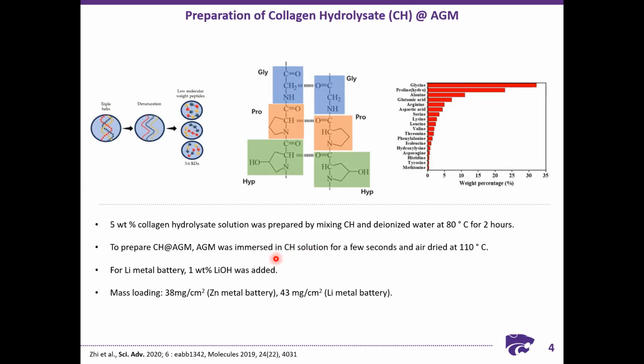They then immersed the AGM separator inside the CH solution for a few seconds and dried it at around 110 degrees centigrade. Based on the difference in mass, they calculated that the mass loading is around 38 milligram per centimeter square for the zinc metal battery, and for the lithium metal battery around 43 milligram per centimeter square. Only for the interlayer for lithium metal batteries, they added 1 weight % of lithium hydroxide.